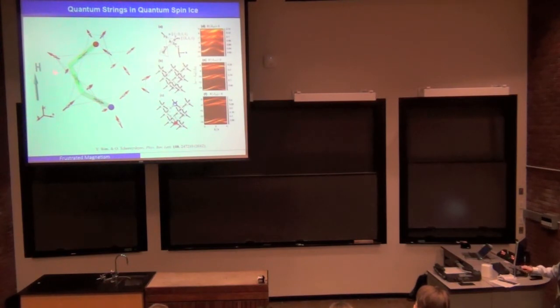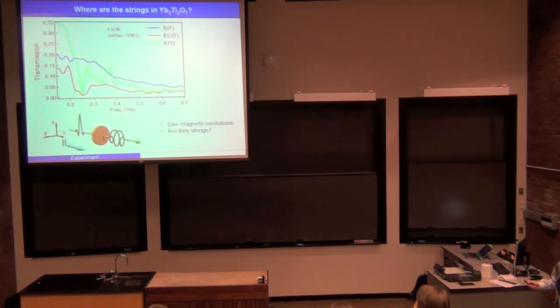So here I showed you a corner string with length 3. So you will need to flip 3 spin to get this corner string, and then it's possible for corner strings to have different lengths, and they would show up in the neutron scattering as different groups of this type of excitation. And this is what we are going to look for in this material using time-domain terahertz spectroscopy.